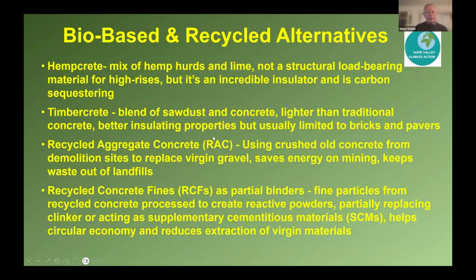And then what do you do with all the old concrete from the buildings you do actually knock down? So you can recycle that, either using the aggregate to recycle that instead of it going to landfill or other ways, or you can actually produce the concrete down to a fines, which is a binder. So these particles will help create reactive particles, which you can use to partially replace the clinker or add to the other cementitious materials that you're using. So it reduces the amount of virgin material.